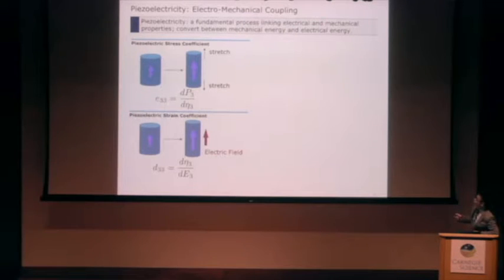Piezoelectricity is characterized by the piezoelectric coefficients. In this presentation, I will mainly focus on the longitudinal response, which is the response along the polar axis. There are two piezoelectric coefficients. One is e33, which relates the change in polarization to the change in strain. Another one is d33, which reflects the strain change in response to an external electric field. These two piezoelectric coefficients are related to each other through elastic compliance.